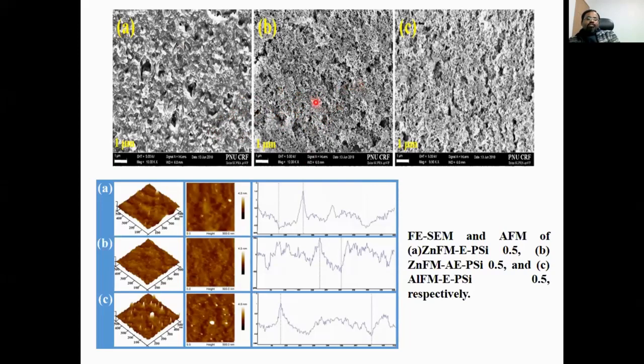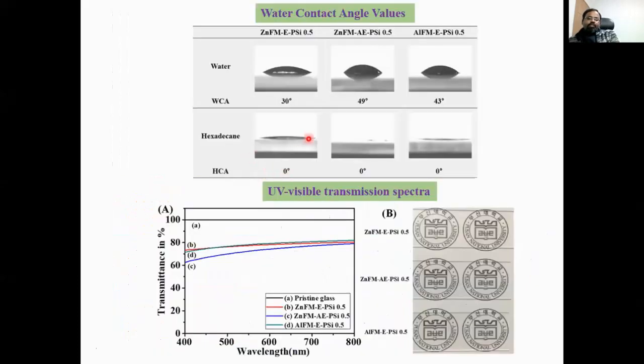Also, this reduces the transparency because of the large quantity of silica particles deposited. So we kept it optimized at 0.18% of silica in our coatings, and we just checked the higher amount for a comparison study.